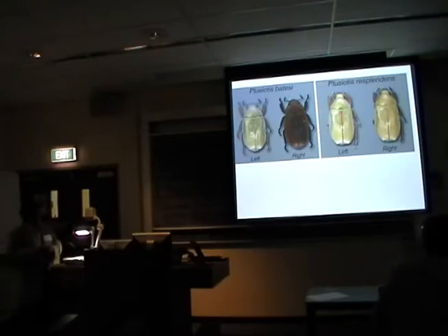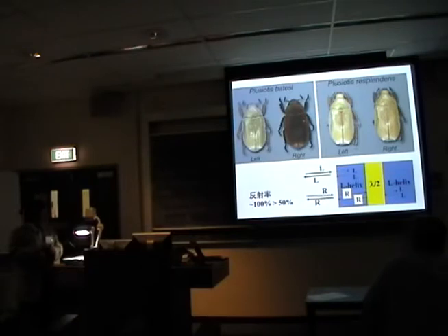And how can they reflect both left- and right-handed light? You can guess how they do. It's very simple. They just insert a half-wave plate. If we observe the cross section of the skin, we can actually observe the helical structure and the half-wave plate nematic. So this is the uniaxial half-wave plate nematic, and the left-handed helix.